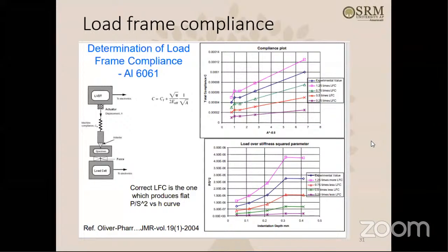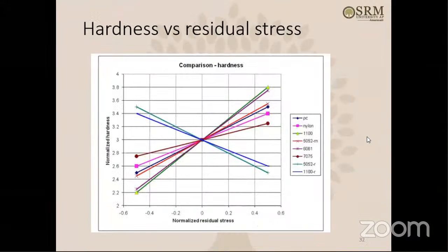So coming to the final calculations here, as you can see, the hardness and the stiffness basically. When you vary the residual stresses, the 0 is the no residual stress, the right side is the tensile residual stress, and the left side is the compressive residual stress. You can vary from the compressive residual stress of 0.6 to the positive 0.6 level, and these values are normalized. So as you vary the residual stress from the highest compressive level to the highest tensile level, what happens to the hardness? That's what is showing here.